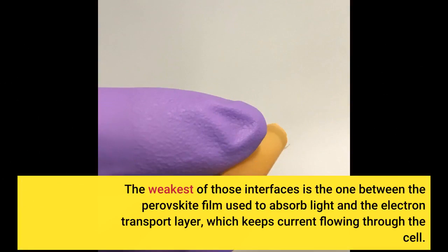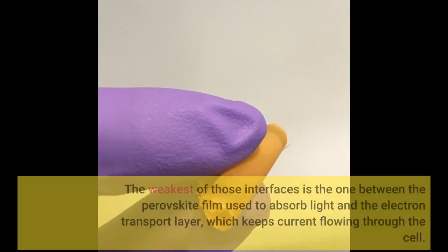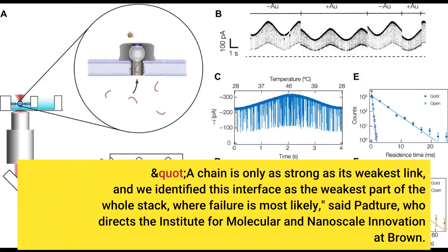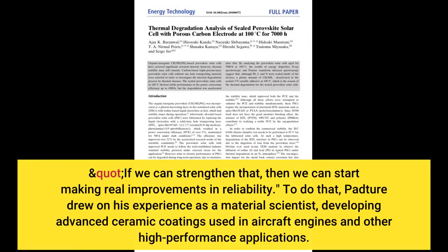The weakest of those interfaces is the one between the perovskite film used to absorb light and the electron transport layer, which keeps current flowing through the cell. "A chain is only as strong as its weakest link, and we identified this interface as the weakest part of the whole stack, where failure is most likely," said Padture, who directs the Institute for Molecular and Nanoscale Innovation at Brown. "If we can strengthen that, then we can start making real improvements in reliability."